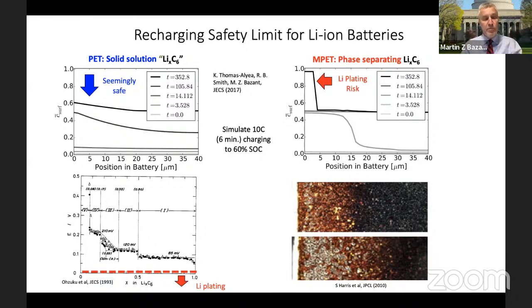The way lithium-ion battery works is you want to insert lithium into graphite and then get it back again reversibly. You do not want lithium going into lithium metal. That gives you inefficiencies and ultimately even safety concerns. And it was already shown in the 2010 experiments that lithium metal can form at high rates. That's the silver color you see here. And in fact, it's clear looking back that it only forms on top of the yellow particles, which are full.